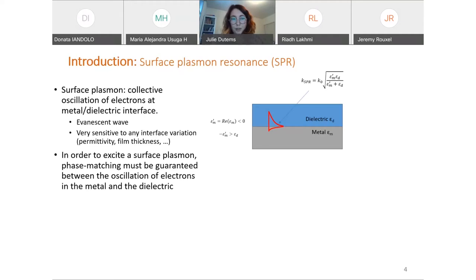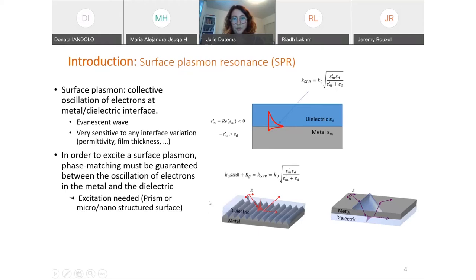To achieve that, we can use a prism or a micro and nanostructured surface. What is the difference between both? It is that for the prism, for the light incident on the prism to go through the metal, it must be optically transparent. And so in my thesis, since I am studying passive film, it means that there is an oxidation of the metal, which means metal will be consumed. So if I have a metal that is really thin, there's a huge chance that the entire metal will be consumed.